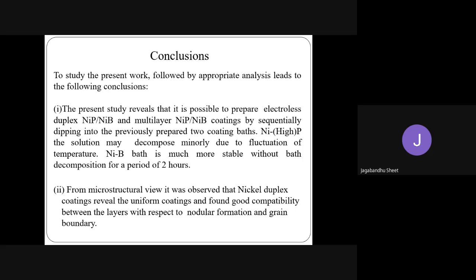From the present work, the following analysis led to the following conclusions. The present study reveals that it is possible to prepare electroless duplex NiB by NiP, that is, NiB as the outer layer, and multi-layer NiP and NiB coatings by sequentially dipping into the previously prepared two coating baths. For NiP, the high phosphorus content is used, that is, Ni high P.